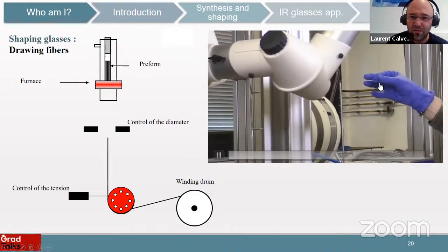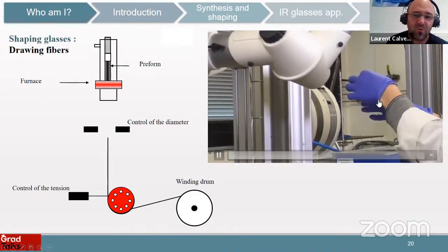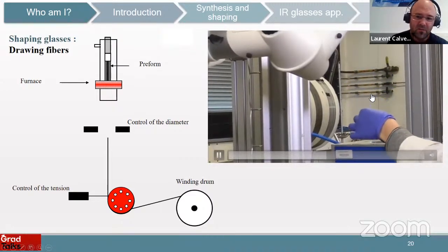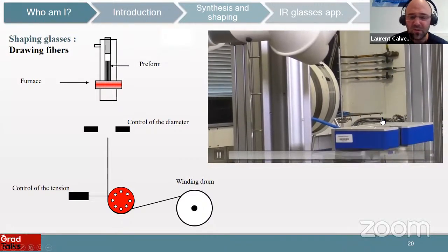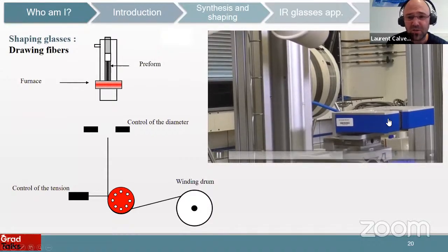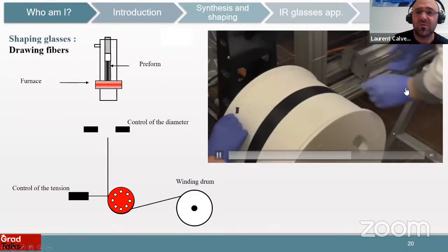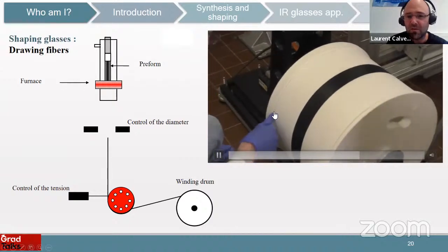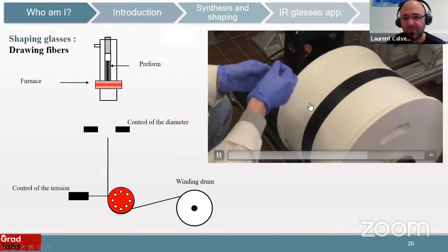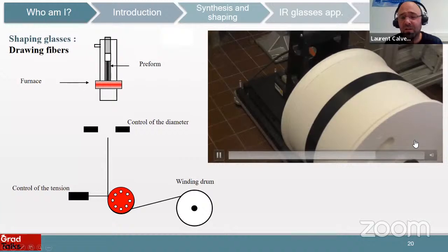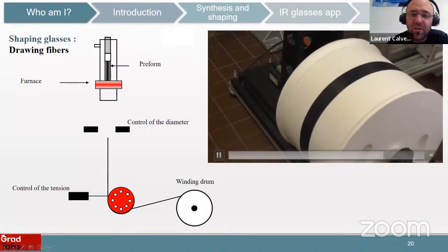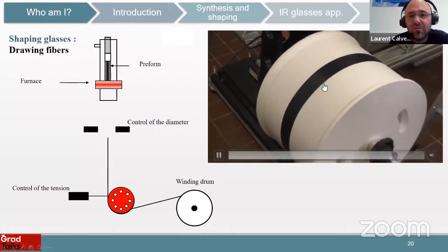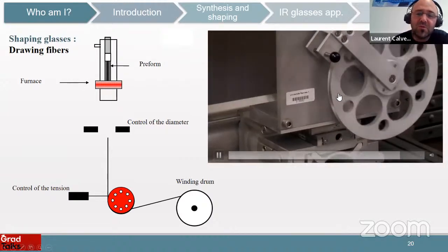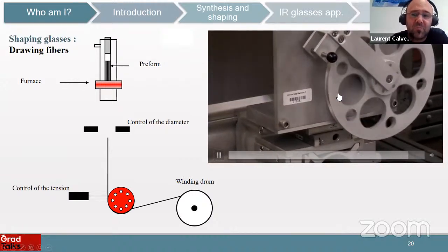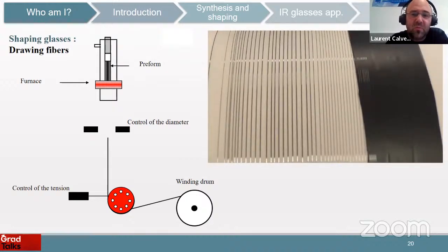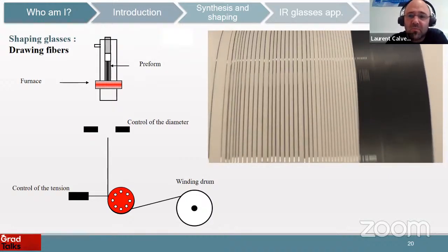So if it's solid, it's very thin here, so you can break the drop and get the fiber. Then you go through this kind of machine, which just serves at controlling the diameter. You stick it on a drum, and then depending on the speed of the drum, you will be able to control the tension. And if you control the tension, then you will be able to control the diameter of the fiber.